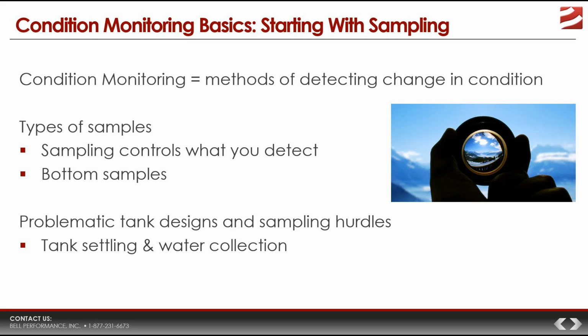Now, they can be trimmed by the fill end, like we were just talking about, which creates, I would say, an ideal situation, where the water is easiest to remove because the fill end is easiest to get at. But you could have a tank that's trimmed by the turbine end. This makes water removal a lot more difficult. You can have a tank that sags, where the center of the tank is actually lower than both of the ends, which makes water pool at the ends of the tank. You can have a hogging situation where the ends are actually lower than the center line. That makes water pool at the intersection of the longitudinal and what they call the transverse latitudinal center lines. And it's also not uncommon at all.